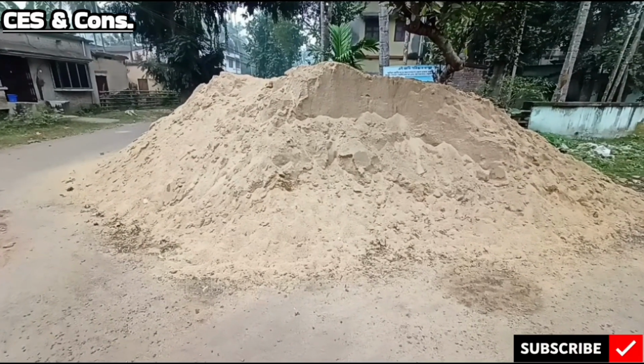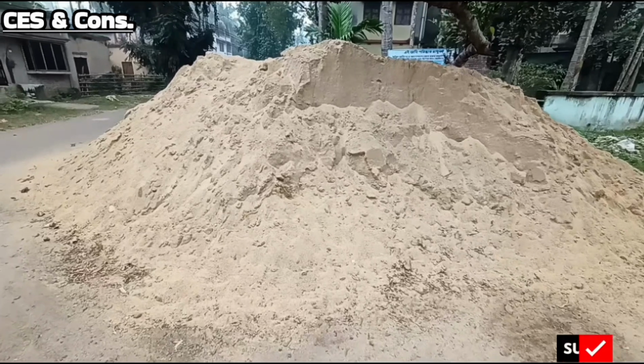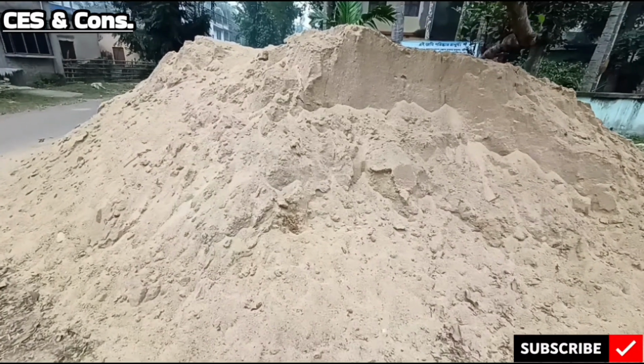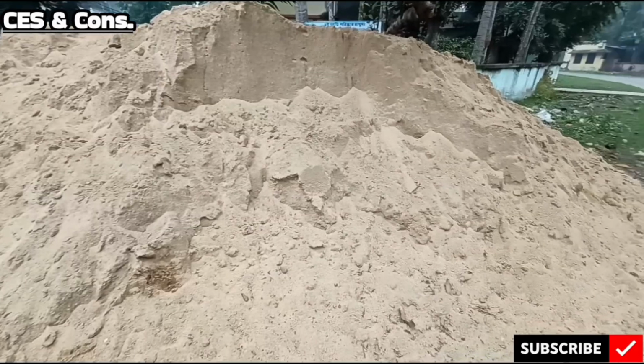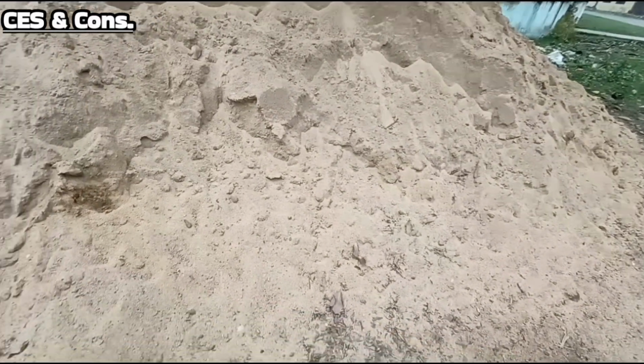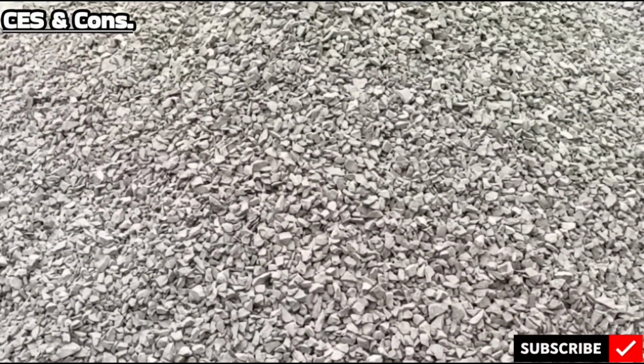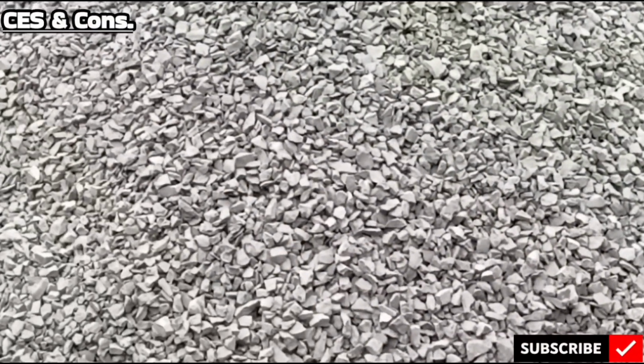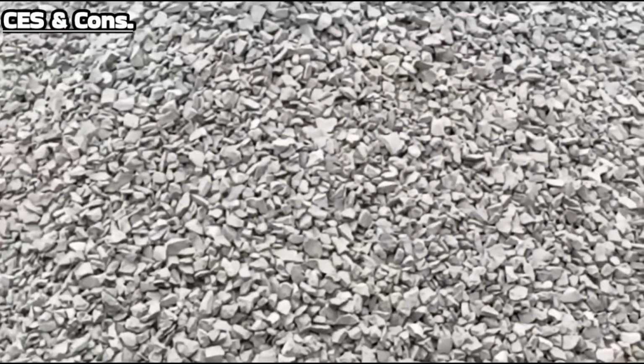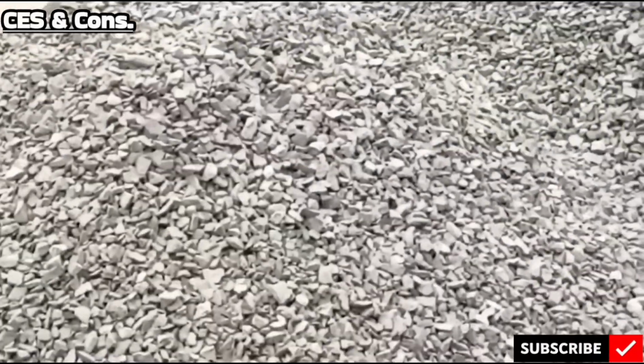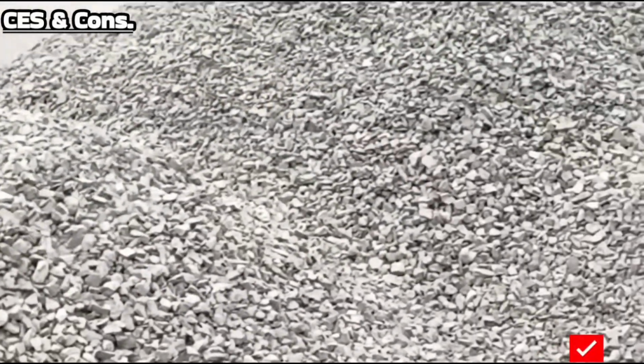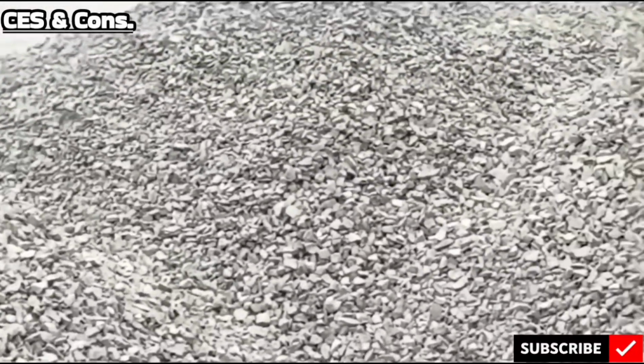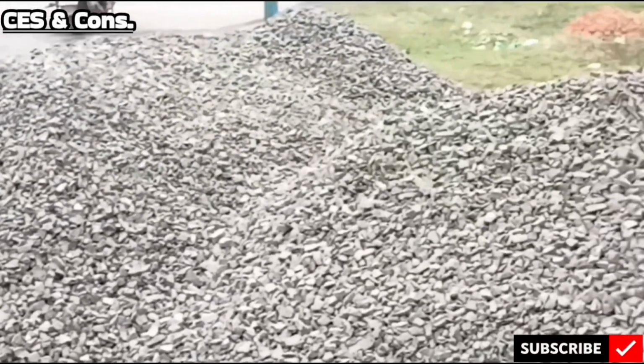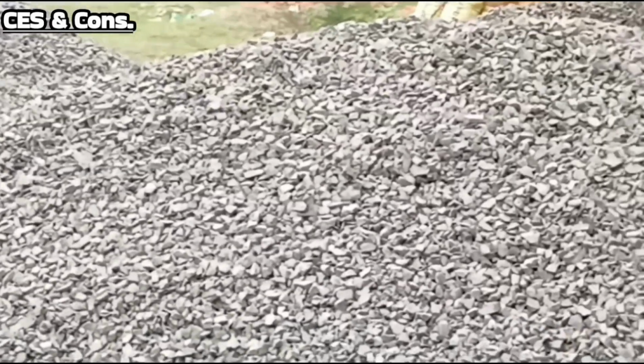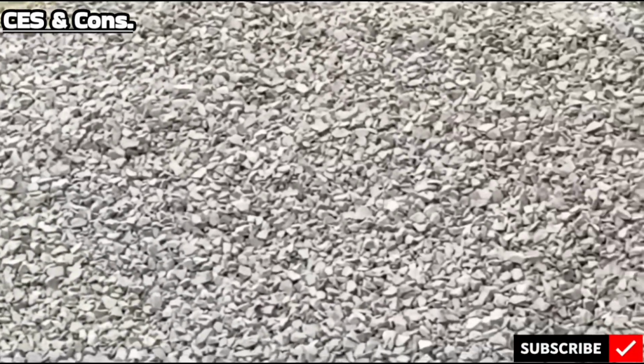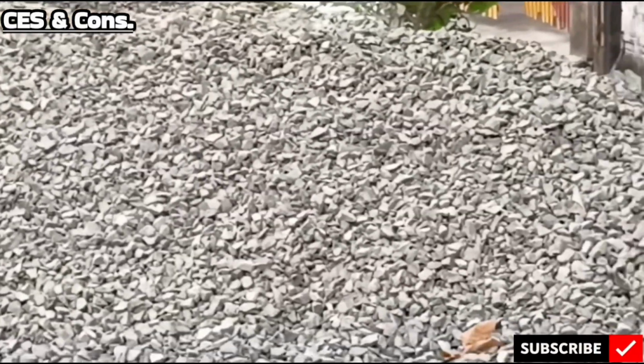This is fine aggregate, that is natural sand. Sand should be clean, well graded and preferably from Zone 2. This is as per IS 383-2016. The coarse aggregate, that is stone chips, should be as per Indian Standard Code of Practice 383. The size must be 20 mm down, angular and hard enough. Water for concrete should be as per Indian Standard Code of Practice 456-2000. This should be potable quality, free from harmful salts and pH should be more than 6.